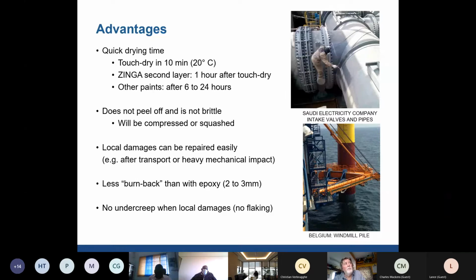Whether you apply it with airless or whatever beforehand, the damage can always be touched up with a roller or a brush, and it will blend in with the rest of the Zinga. So you won't see any touch-up marks after a few days. When you're welding Zinganized steelwork, your burn back is 2 to 3 millimeters, which means that on each side of the weld, you're going to lose up to 3 millimeters in width of zinc. With paint, at least 70, 80 millimeters will burn off both sides of the weld. Then you have to recoat all that.